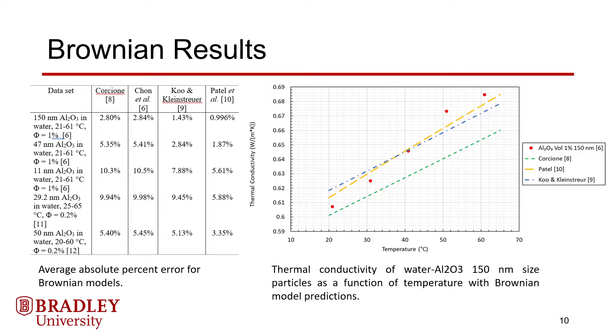The figure shown compares the Corcione, Patel et al., and Koo & Kleinstreuer models with experimental data for Al2O3 nanoparticles for thermal conductivity as a function of temperature. The errors for these models are given in the first data set on the left. Since the Corcione model underestimated the thermal conductivity at both room temperature and high temperatures, the error was higher, but all three models predicted the change in thermal conductivity with temperature fairly well, especially compared to the EMT models. All of the Brownian models performed best when investigating large particles and got less accurate with smaller diameters. Patel's model consistently had lower errors than the other models. The Koo & Kleinstreuer model also performed better than the Corcione and Chon et al. models at large diameters, but the difference in errors was less significant for smaller particles.